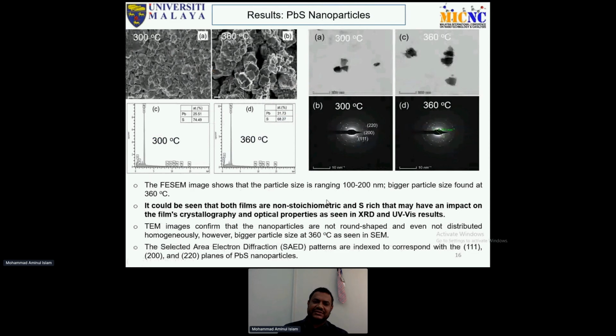Here are the FESEM images. We see the grain growth is also a bit higher for the 360 centigrade, and here are the TEM images. We see that the nanoparticles are not uniform in shape, and the shapes are not distributed homogeneously, but the size is higher again for the 360 centigrade. And here is the EDX. We see that the composition is different for the 2 different temperatures. Due to this compositional change in the lead sulfide, maybe the other changes you see in the XRD and UV-Vis, and even in the SEM images.